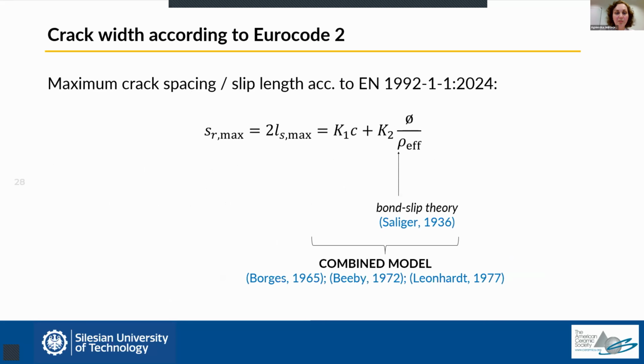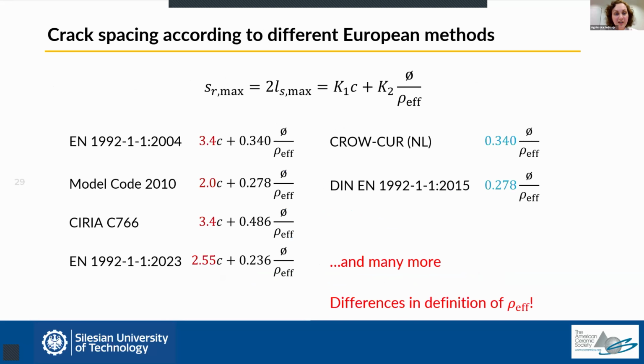And for that purpose, we use the so-called combined model, which is composed of two components. The one which results from bond slip theory, and which relates the slip length to the amount and location of reinforcement, and the other one which directly relates it to concrete cover. And in Europe, you can find a lot of variations of this approach, but all of them follow the same formula. There are two main differences. First of them is whether the concrete cover is taken explicitly into account, because in most of the approaches, the concrete cover is taken into account in determination of the effective degree of reinforcement. And as you can easily see, the difference lies in the values of constants in this approach. So this is basically how we do it in Europe.